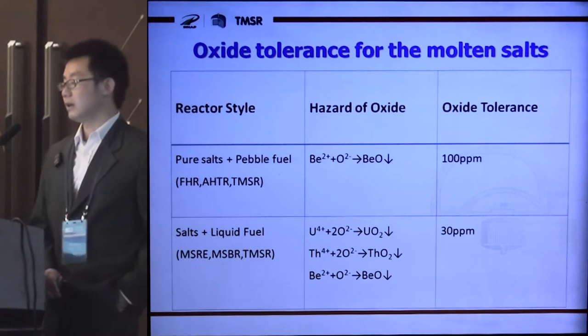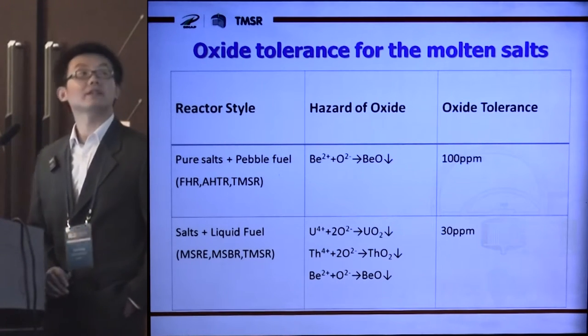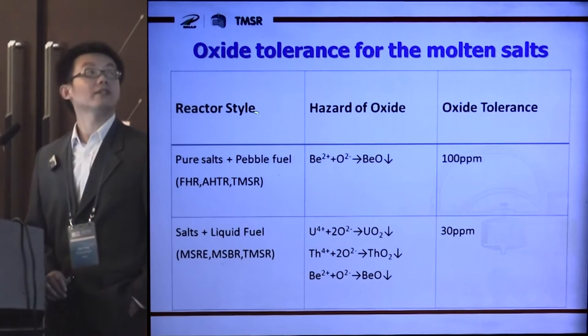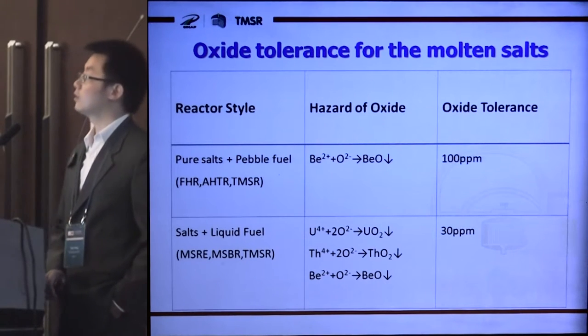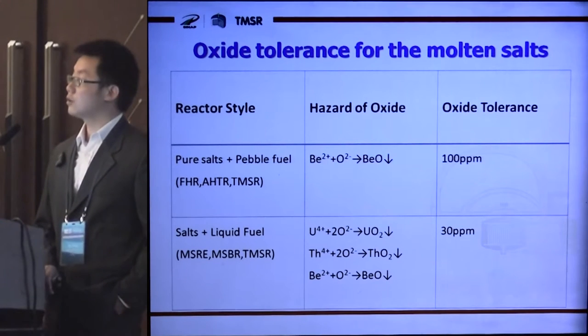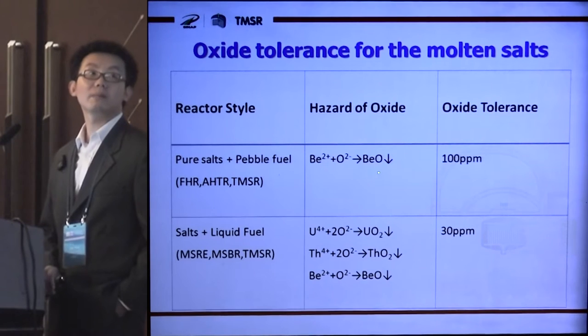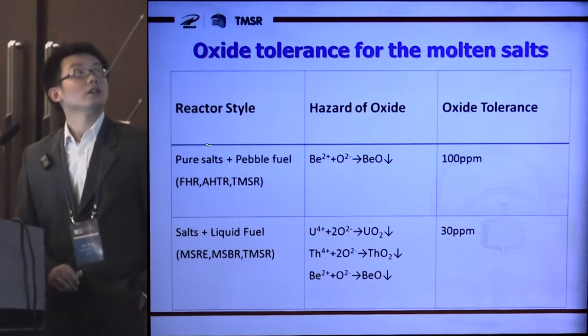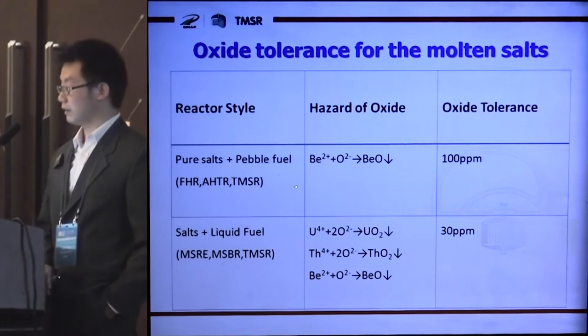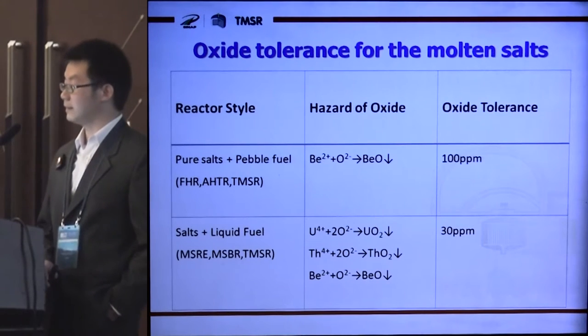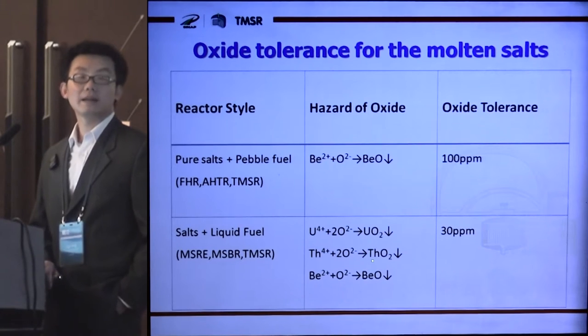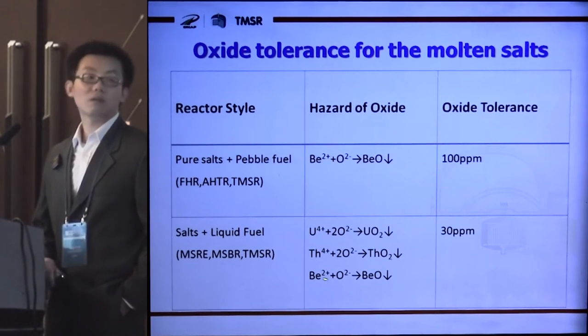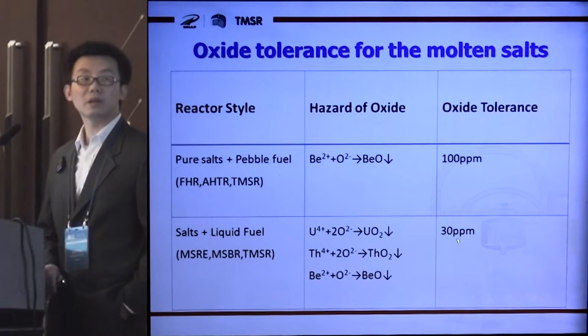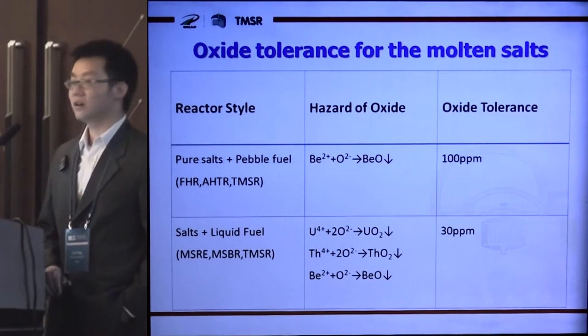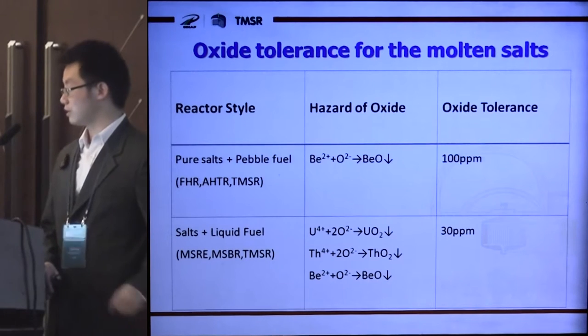The oxide impurity may not corrode the alloy directly, but it may cause other problems. In a reactor with pure salts as coolants, the oxide content in the molten salts should be controlled below 100 ppm to prevent the formation of beryllium oxide precipitation. In the reactors with liquid fuel salt as a coolant, the oxide content should be controlled more strictly because the solubility of uranium and thorium oxide in a molten salt is much lower than that of beryllium oxide. The oxide content in this system should be controlled below 30 ppm according to the suggestions from MSRE, and this is a challenge for us.